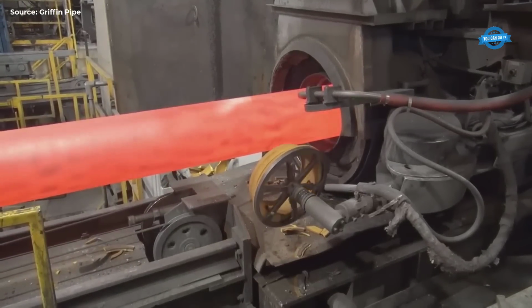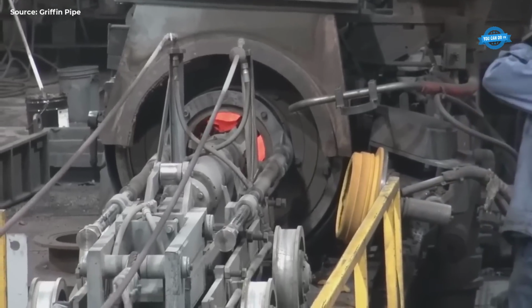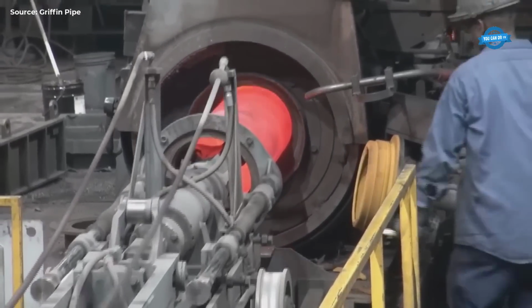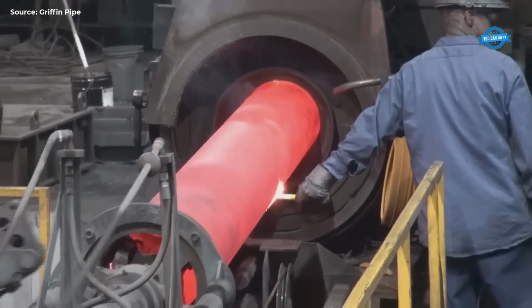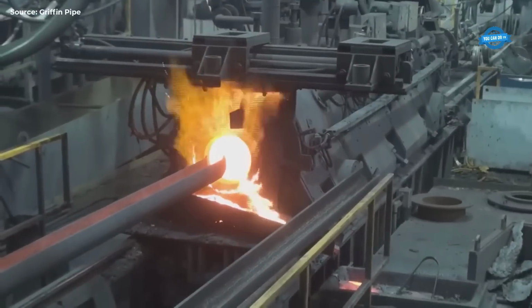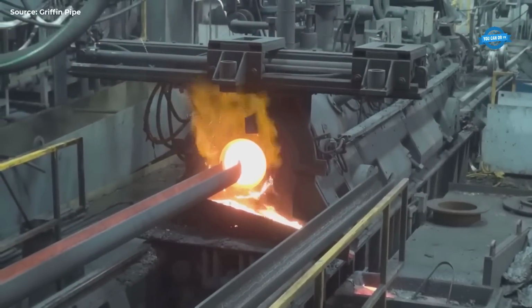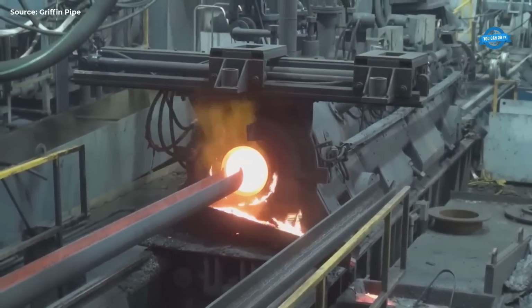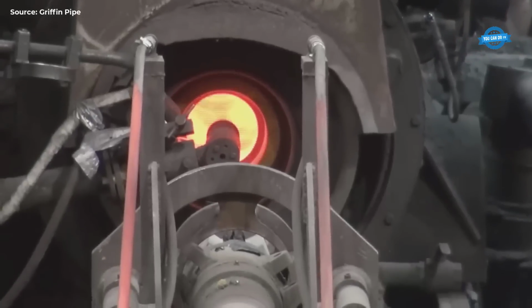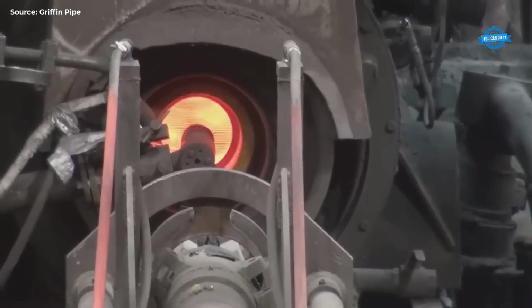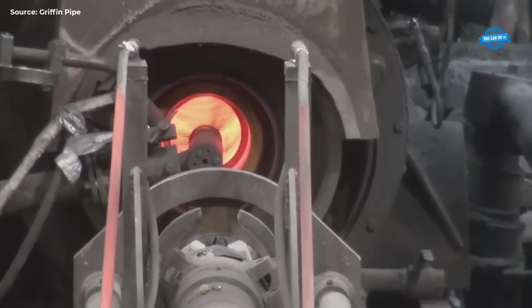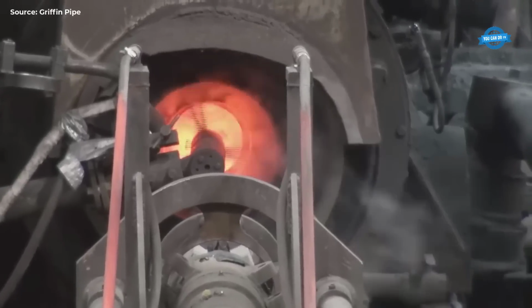Peening and solidification. The mold's inner surface features a bumpy pattern known as peening, which helps the liquid iron adhere to the mold walls, preventing splashing and ensuring a defect-free cast. The centrifugal force also acts as a self-cleansing mechanism, forcing impurities like slag and gas to the inner surface of the pipe, where they have no detrimental effect.